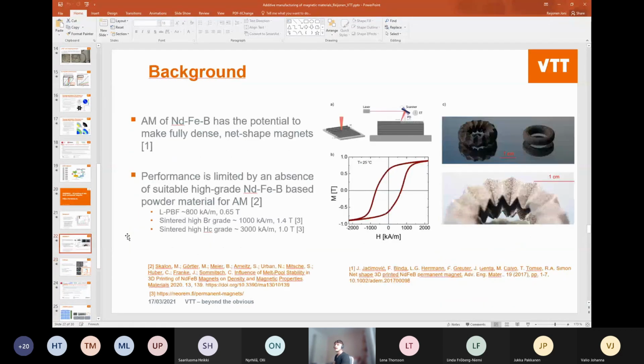But since then, it has become evident that using the alloy that they used, and we've also used in other research groups, the specific powder for making these magnets, this is the maximum you can get out of this alloy by using laser powder bed fusion to process it. So to go further, we need an alloy which is tailored for the conditions of this process, which are highly different from the conventional sintering. Actually, the powder that was used in this example is a powder that was originally intended for bonded magnets.